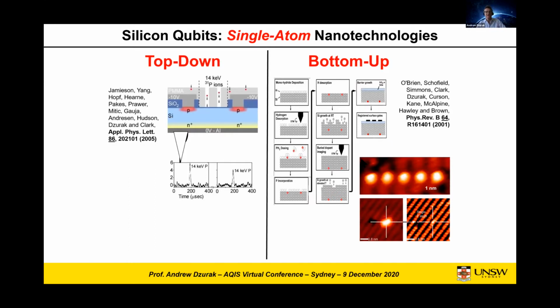And the one that Bruce Kane was thinking of at the time, and the one that was the first one pursued at UNSW, was this technology whereby one can take a very clean silicon crystal, coat it with a monolayer of hydrogen atoms, and then use the scanning probe tip to remove individual atoms to expose dangling bonds. And then phosphine gas can enter into the vacuum chamber, and the phosphorus from the phosphine can bond to those dangling bonds. And then with an anneal step, those can be buried into the surface. The hydrogen can be removed, and then this can be overgrown with silicon. So this original idea, dating back to the late 90s, was then developed in real experimental demonstrations at UNSW in the early 2000s. And this work has since then really been championed by Michelle Simmons at UNSW.